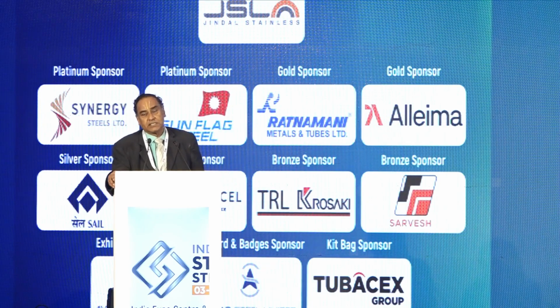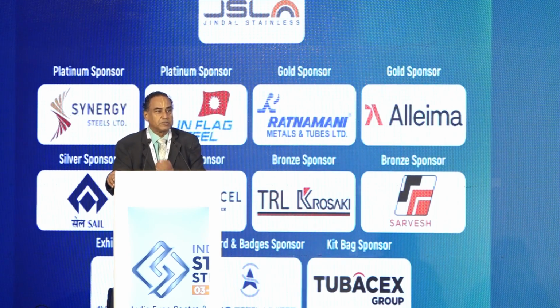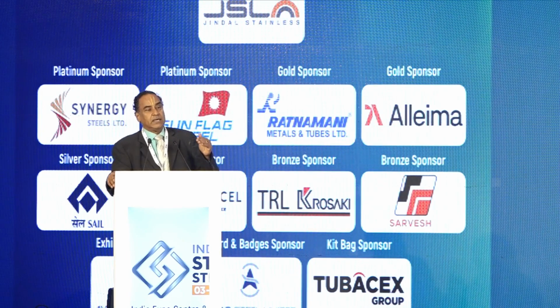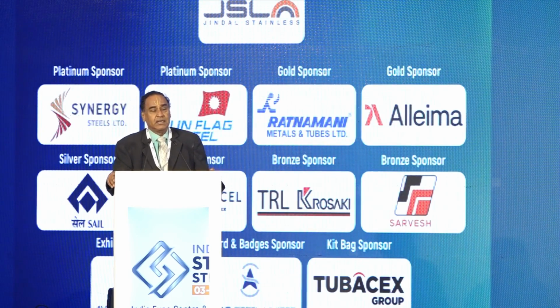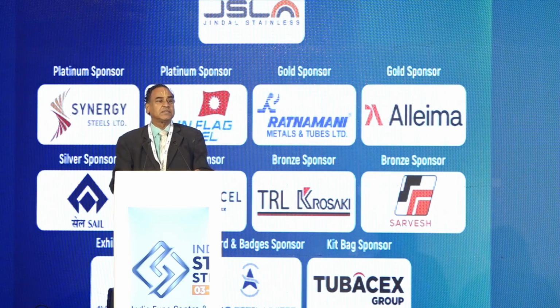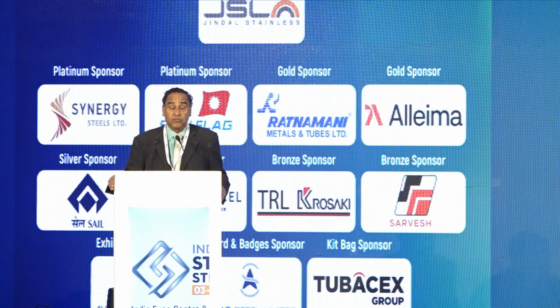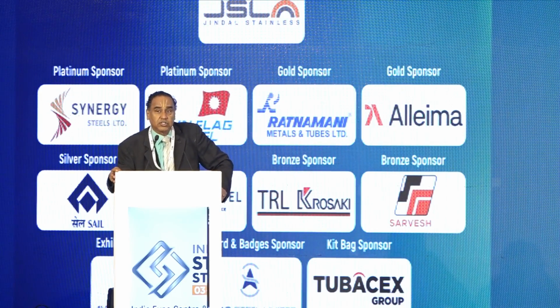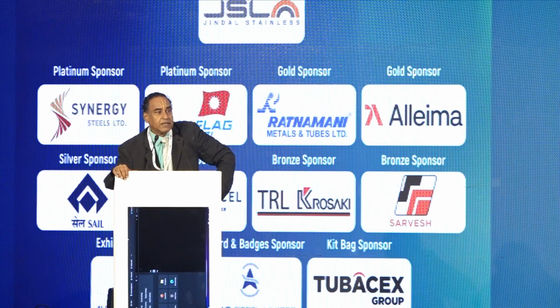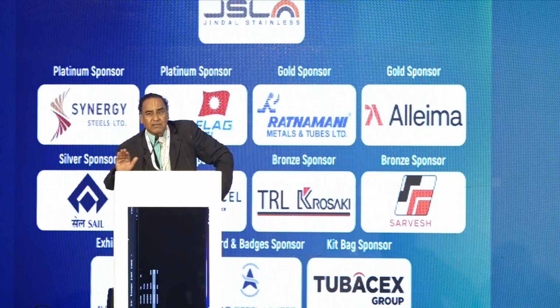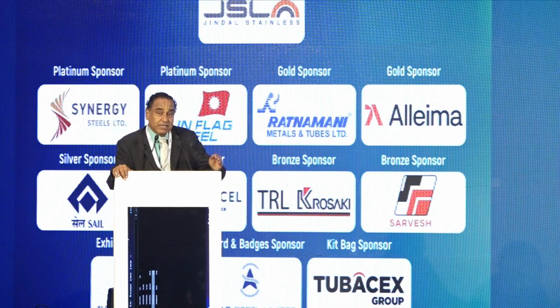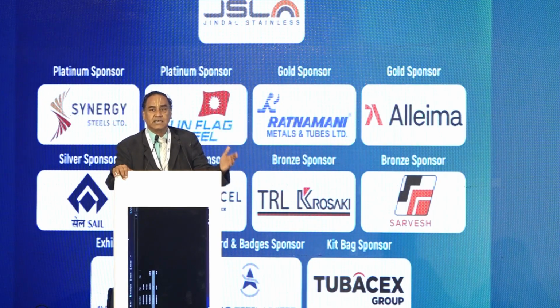The austenitic stainless steels, in comparison, contain chromium, nickel, and molybdenum to impart some special high temperature properties. They are very malleable and highly ductile, and they can be formed, easily welded, and easily fabricated. Because of that, the choice would fall on the austenitic stainless steels, even though they are higher cost because of the presence of nickel or molybdenum. These are preferred materials for general ease of fabrication and ease of operation. Among the austenitic stainless steel grades, the 18.8 base grade is the workhorse grade, that is 304.